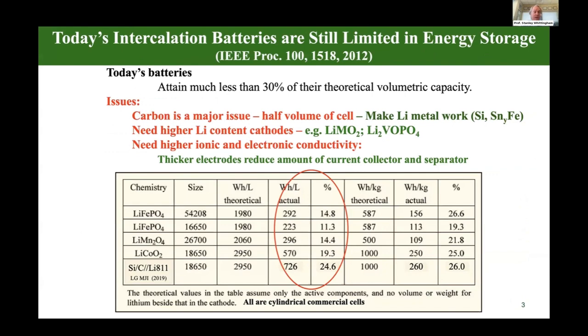And the rationale for this whole consortium is that the present lithium batteries have a much lower energy density than they're theoretically capable of. So look at what's inside this oval I've shown you here. The volumetric energy density in commercial cells, and these are mostly cylindrical cells, is from 11% to 25% of theoretical. So a huge opportunity to increase that. On the weight basis, exactly the same thing, about 25%. So our goal is, in fact, to get this up to 50% and this up to 500.